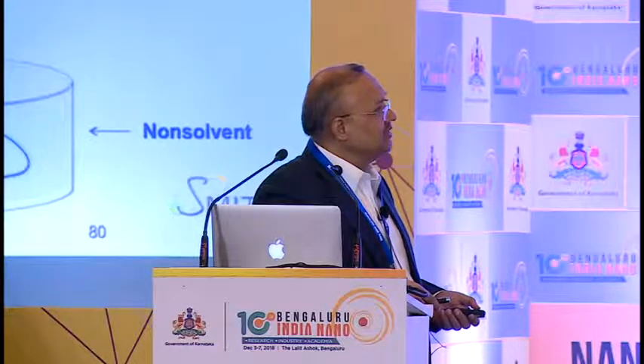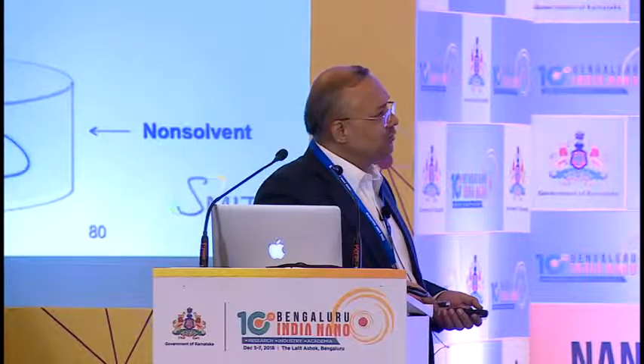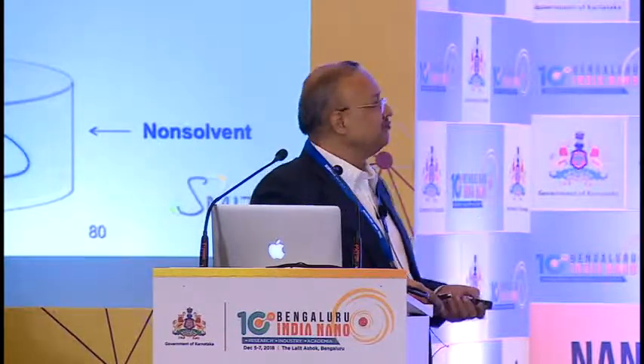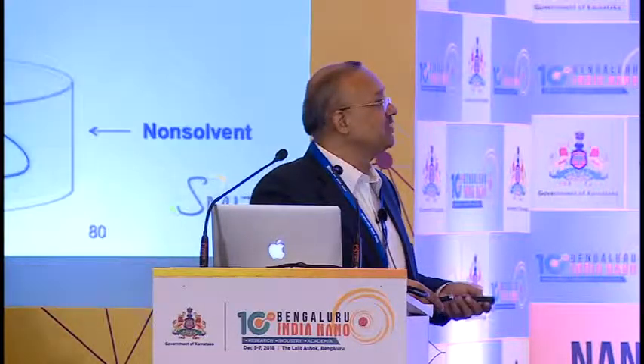microns long. We did a hollow spinning, solution spinning, where the wires were put in an aqueous media and put inside the fiber, and the polymer solution was put outside that, and it was co-spun together into a hollow structure. And this is the kind of hollow structure we created. So there is a skin of polymer, and there is a nanowire layer deposited right inside it, and then there's a hollowness. And we could create fibers of various diameters just by simply changing the flow rates of the core fluid in various ways. And obviously, with the concentration of nanowires, we could create various kinds of structures. So we created a lot of structures.